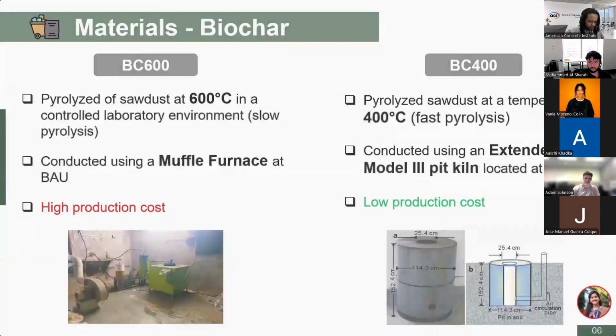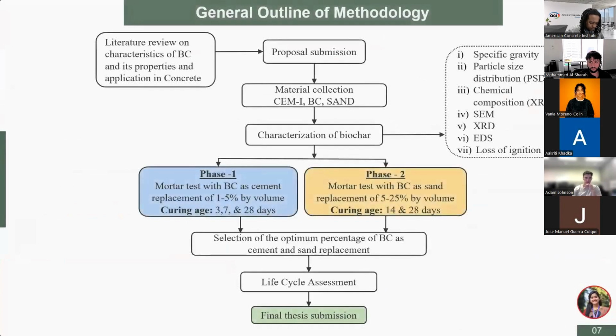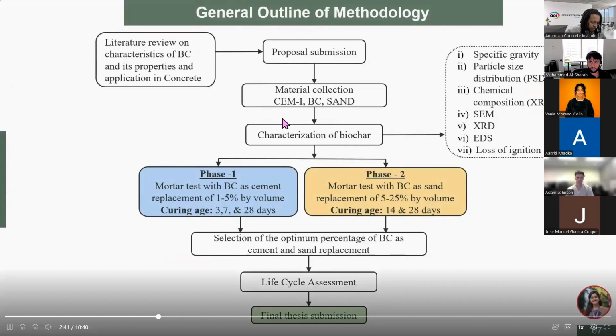This is the general outline of our methodology. After collecting the biochar, we tested the characterization of this material. After that, cement was replaced with biochar by 1 to 5% by volume with a curing age of 3, 7 and 28 days. Then sand was replaced with biochar by 5 to 25% by volume with a curing age of 14 and 28 days. Then the necessary tests were conducted. Then we did a full-fledged life cycle assessment of our approach.